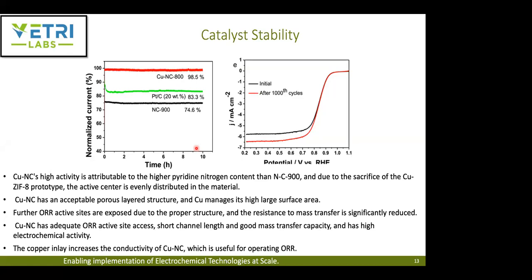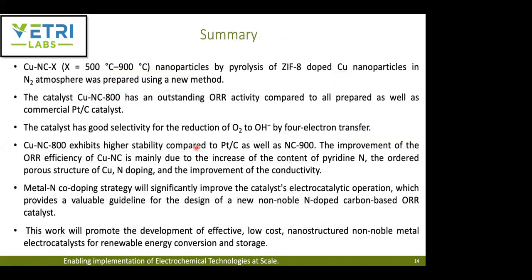So as a summary, they prepared the CuNC by using pyrolysis of ZIF-8 with doped copper nanoparticles using a new method. And the resulting catalyst had an outstanding ORR activity compared to the commercial platinum carbon catalyst. And it also had a good selectivity towards this 4-electron process. And the CuNC 800 had a higher stability compared to the platinum carbon catalyst and also to the nitrogen doped carbon without any copper.